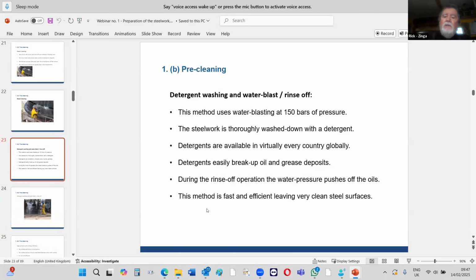The detergent, again, you wash down the steelwork with detergent, and they're available in every country. The detergents break up oil and grease, and it floats to the surface of the water. So while you're jetting, it's coming away from the steel surface. And again, if you put in some bleach, that actually has 2 advantages, believe it or not. When you put bleach in, it still breaks up all the oil and the mess, takes it off the steel, and then you rinse it off.